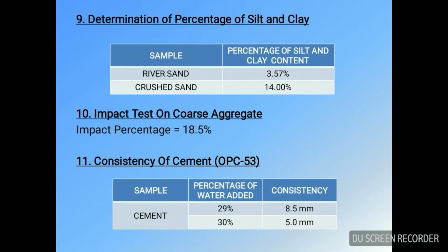Next comes the determination of the percentage of silt and clay. In this, a 100 gram sample of river sand and crushed sand was taken in a 75 micron sieve, after which it was held under running water. The running water was continued until we saw clear water. After we reached clear water, the sample was weighed again and the change in weight was noted. At the end, we saw that for river sand it came to about 3.57%. For crushed sand it came to around 14%. The allowable limit for crushed sand is within 15%. Within 15%, so this material was used.